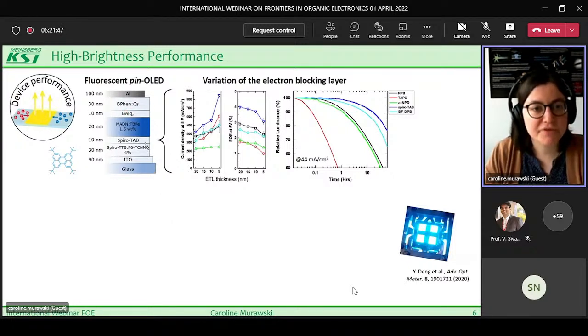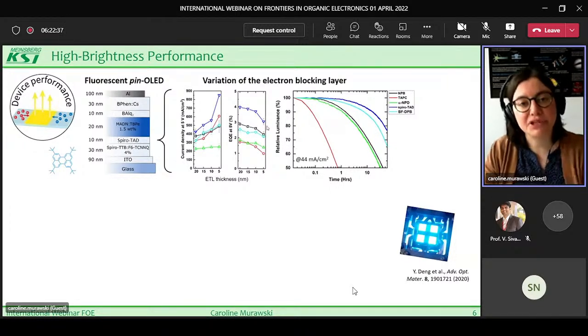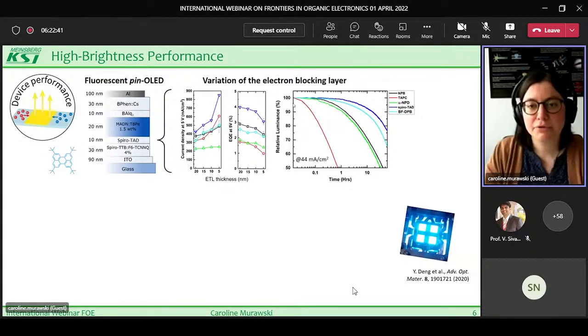We did some variations on the stack. One example shown here is a variation of the electron blocking layer. We used these 5 different materials: NPB, TAPC, alpha-NPD, Spiro-TAD, and BFDPB. On one side, we wanted very high current densities, and we studied this also as a function of the thickness of the emission layer. Of course, with thinner emission layers we can get to higher current densities. But if we look at the EQE at 5 volts for these different devices, we also see that thinner emission layers have a drop in EQE because some of the emission gets quenched by the adjacent blockers. We also looked at the lifetime of these devices, and in both electrical and EQE properties, and also in lifetime, Spiro-TAD was the best candidate for us.